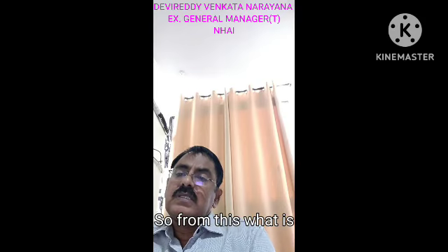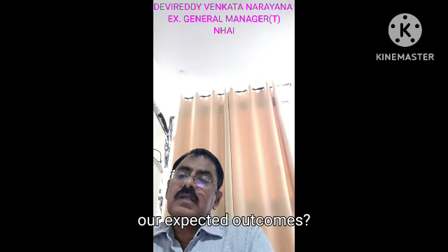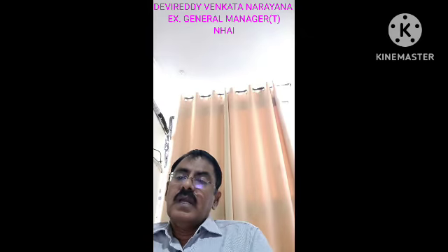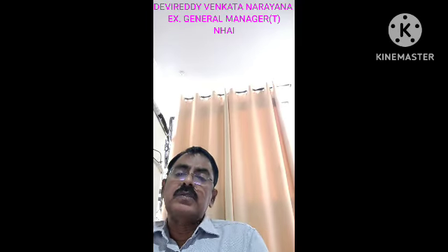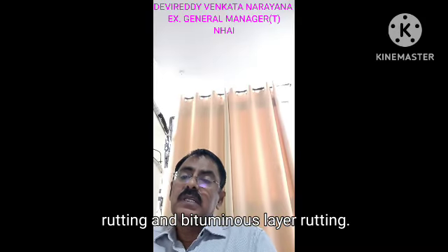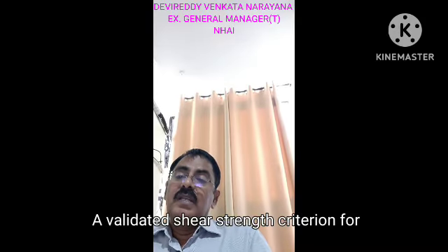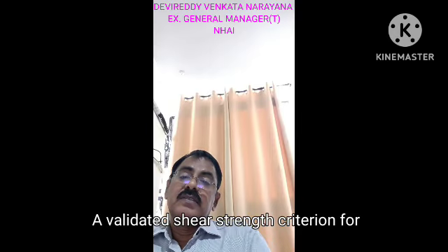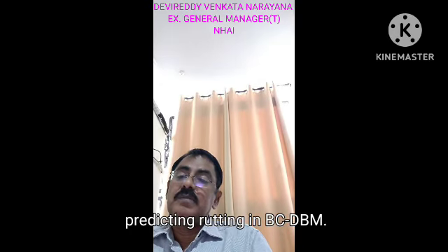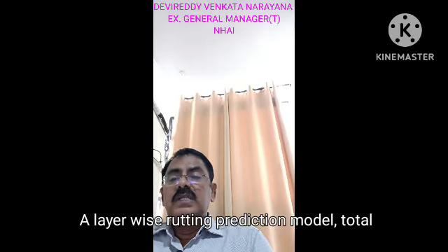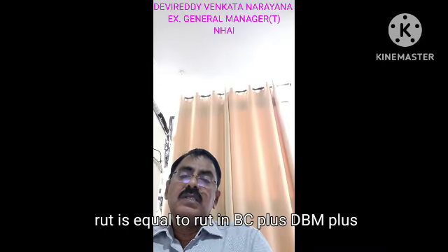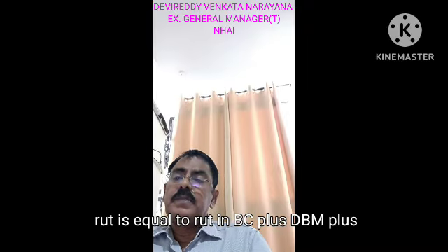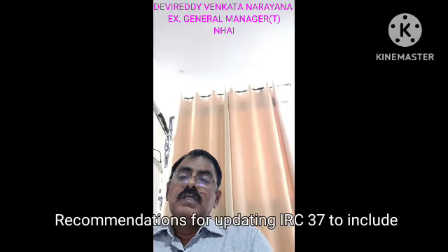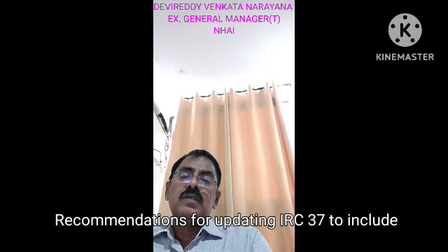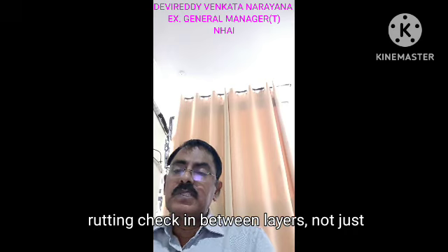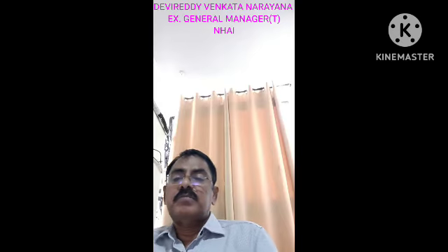So from this, what are our expected outcomes? Clear distinction between subgrade induced rutting and bituminous layer rutting. A validated shear strength criterion for predicting rutting in BC and DBM. A layer-wise rutting prediction model: total rut is equal to rut in BC plus DBM plus subgrade. Recommendations for updating IRC 37 to include rutting check in bituminous layers, not just mix tests.